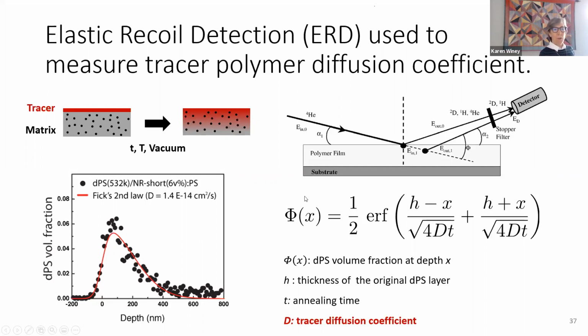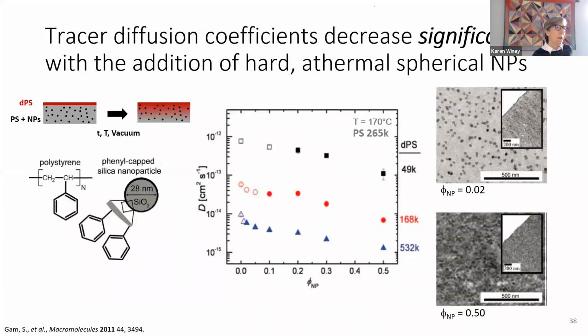So this diffusion coefficient here, the only fitting parameter you have is the diffusion coefficient. H is the initial thickness of the tracer layer, and T is time. And we experimentally measure this concentration profile as a function of X, depth into the sample. And so in our first set of experiments with spherical particles, we did this with nanotubes first, but I'm only going to show you the spherical particles today.